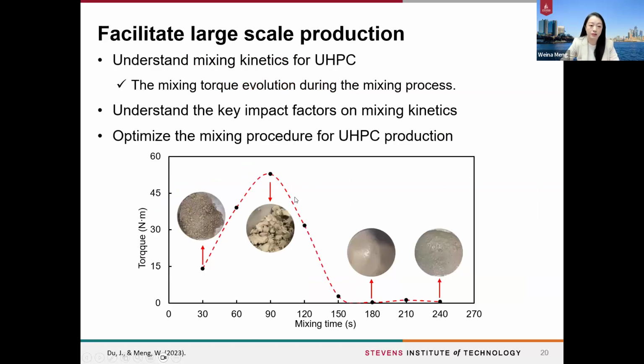So for the third problem, to address that, in order to facilitate the large-scale production of UHPC, we should first of all understand the mixing torque evolution during the mixing process. The most difficult time is when the materials transform from solid to liquid. After that, the torque will reduce to very, very small, and it represents the homogeneous time. And also by understanding the key impact factors on the mixing kinetics, we could optimize the mixing procedures for the UHPC production in large scale.